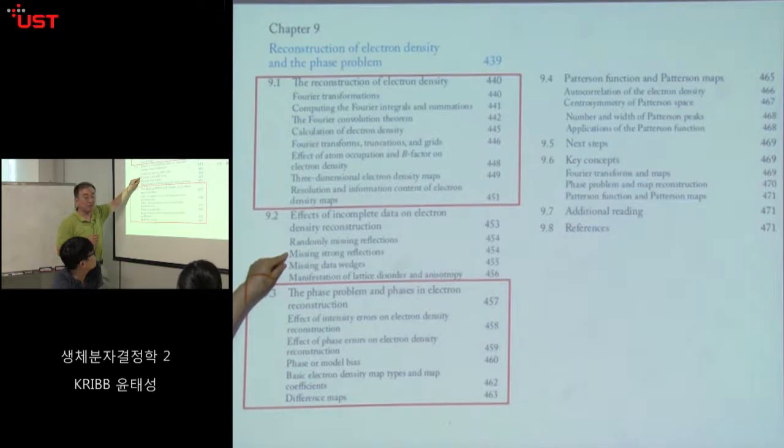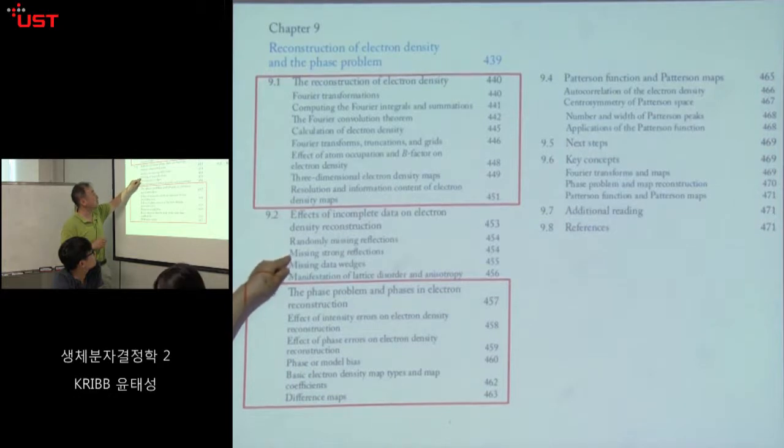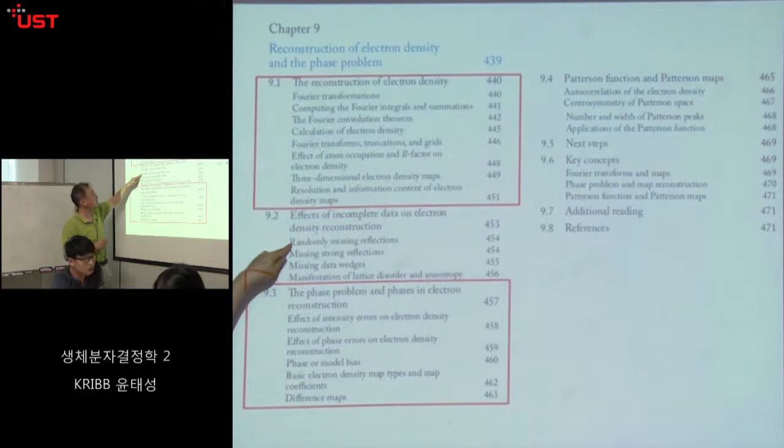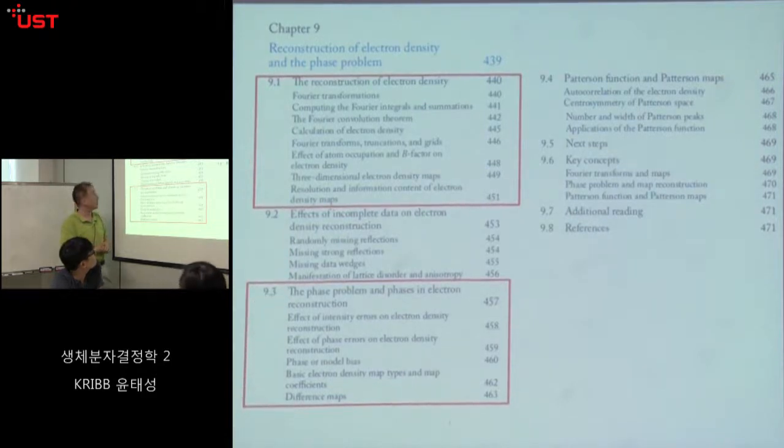His crystal was so well diffracting that with just the smallest exposure time, 1 second, we had saturation on the detector. So we cannot measure strong spots accurately. In such a case, we may experience missing strong reflections. Missing random reflections cannot be a serious problem, but missing strong reflections can be a problem.